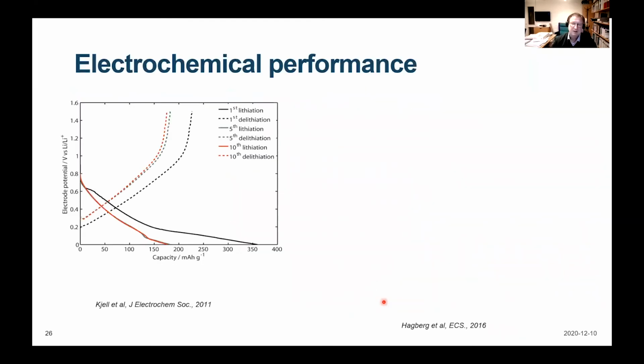And of course, then we need to characterize these materials. So we need to be able to characterize the electrochemical performance, the capacity, how much ions do we get in, how much energy can be stored. So we typically do galvanostatic or potentiostatic cycling of the batteries. And this is showing a galvanostatic cycling. We look for the capacity of the carbon fibers and the half cell only.